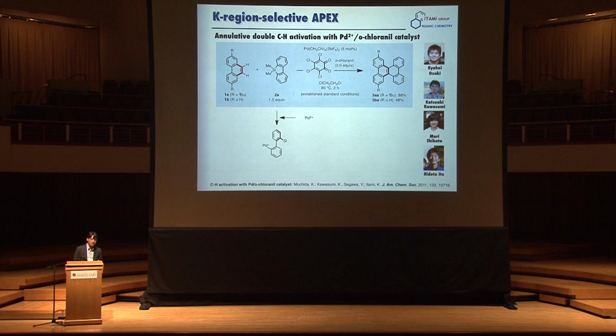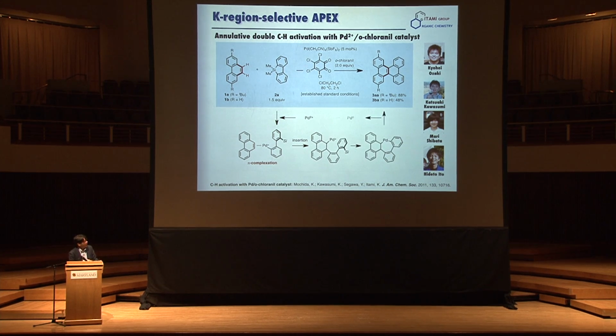Here I'd like to show the mechanism. The first step is the transmetallation of this dibenzosilole with palladium(II), forming biphenyl palladium. The second step is pi complexation of PAH, followed by Heck-like insertion, second transmetallation, reductive elimination, and oxidation forming the APEX product, and the palladium(0) is reoxidized to palladium(II) by o-chloranil. This is very selective to the K region because the K region is the most olefinic or least aromatic. And this is very, very predictable. There are a bunch of examples.